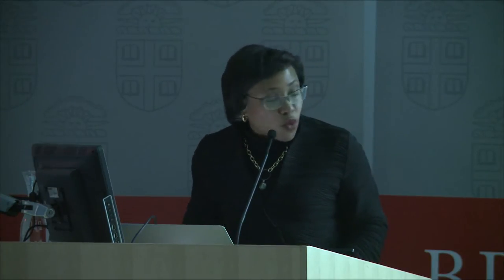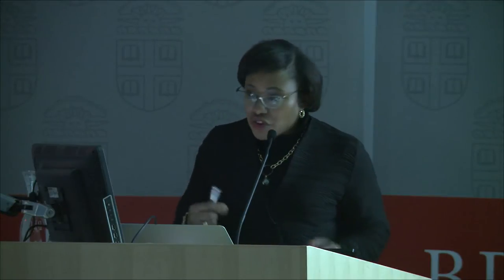And when we're just at 1 folate per cluster, we are not optimizing the amount of binding that we can get in these systems. However, we do see that there's an enhancement in binding avidity, and we see an enhancement in uptake. And we should see some sort of optimization when we get to this 5 to 6 number. What's interesting is that we actually see this occur at 3 rather than 5 to 6.